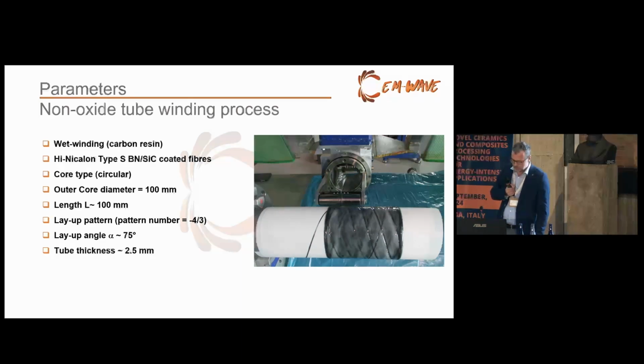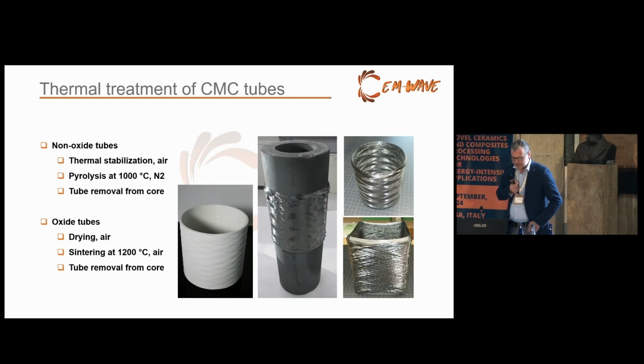And we focused on the lay-up angle of 75 degrees, and the tube thickness here was 2.5 millimeters. As you can see here, afterwards this material was then pyrolyzed, and again there we had the problem because with only a small amount of residual carbon we had such a weak mechanical property state that it's really like extremely thin porcelain, and we were the elephant in the porcelain shop, and this was the reason that we really didn't catch in this state the preform to cut the edges.